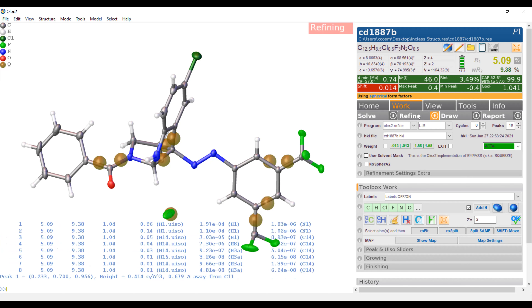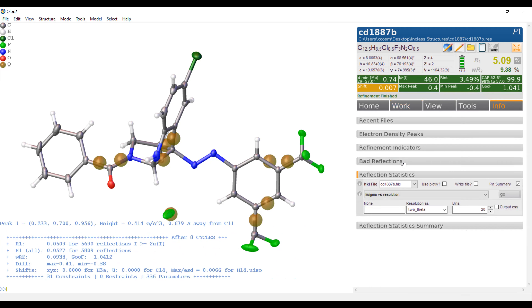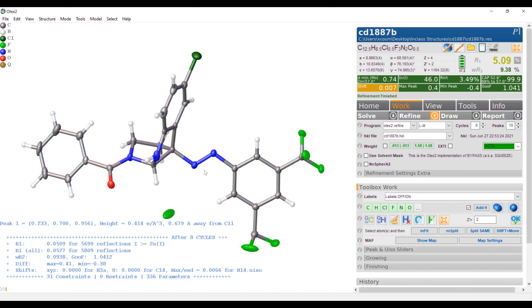Goodness-of-fit is 0.993, R1 is 5.1%, R2 is 10.5% — this is a pretty good structure. We keep refining the weighting parameters until they go green. Once they're green, check your goodness-of-fit — between 1.0 and 1.1 is ideal. Now go back to Info and check for any more bad reflections, since changing the weighting parameters can sometimes cause reflections to appear with error over ESD greater than 10. Here we're still good. You can roll the mouse down to delete Q peaks or roll it up to increase them.